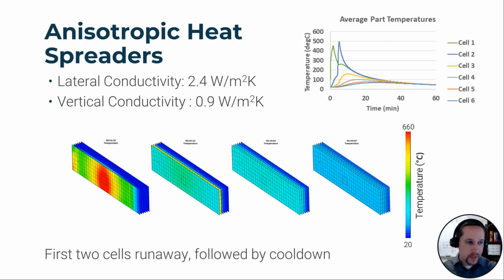So the first case that we looked at was the anisotropic case, which is the most realistic. And this is including the thermal conductivities as measured by C-Therm for some characteristic carbon fiber materials. And what we see here is for the anisotropic heat spreaders, the thermal runaway actually propagates from the trigger cell to the adjacent cell, but doesn't propagate further through the pack. So we have 2 cells in this case going into runaway, followed by a cool down period.